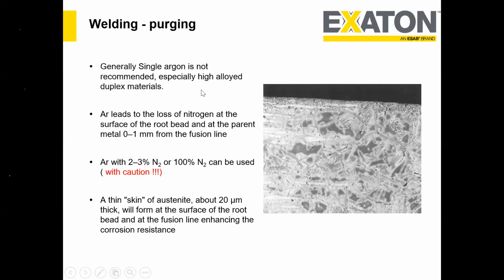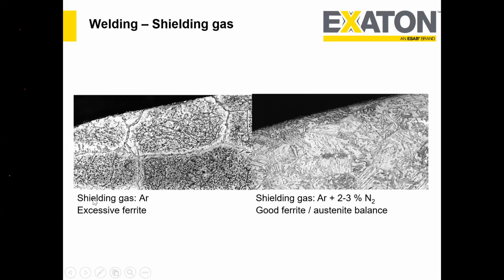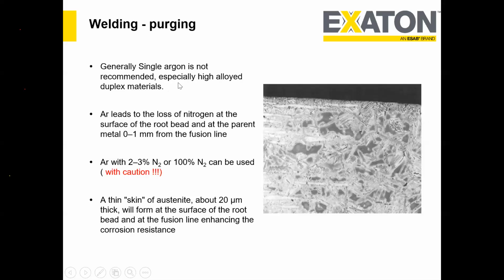Okay, so welding with the purging of the gases. Generally, single argon is not recommended, especially for the highly alloyed duplex material. I have explained that, because if you use argon, there is a potential of having an excessive amount of ferrite and a lesser amount of austenite. So we need a desired microstructure. Argon leads to loss of nitrogen on the surface of the root bead, in the parent metal 0 to 1 millimeter from the fusion line. This is what I explained just now.